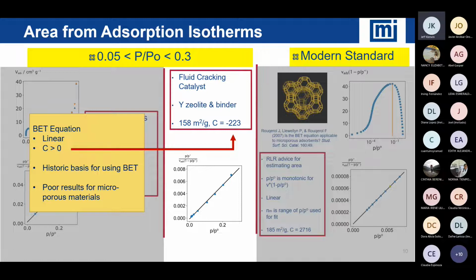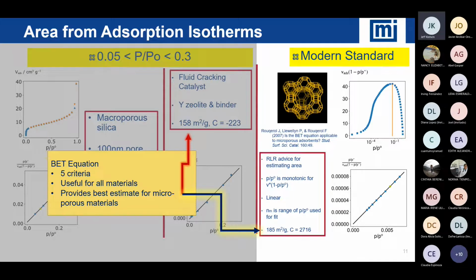So it's really challenging. These historic rules don't work so well for materials that are microporous and particularly important materials. If we look now at the modern standard for calculating surface area, it is much more challenging to calculate surface area on these materials, but we have tremendous rules now for how to practice BET surface area and calculate surface area so that everyone can do it. And we could get very good, consistent results, regardless of who is calculating that. And beyond that, the rules are so well defined that we can calculate surface area automatically. We need much less user intervention, so you no longer need people to decide this is the correct range for surface area. This came about a little over a decade ago.